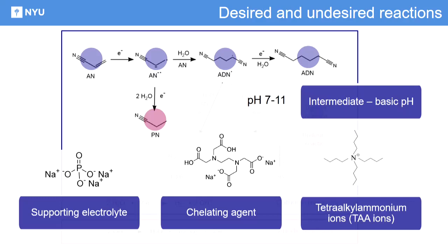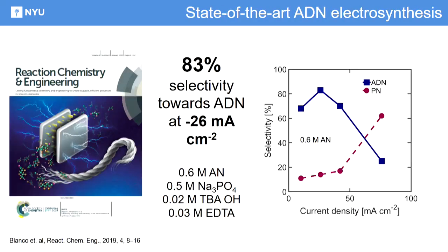So overall, by doing a fairly systematic study on the electrolyte, we were able to find conditions that led to fairly high selectivities, which are starting to approach those reported in this electrochemical process in industry. What we also found is that as you increase current density, of course, the selectivity towards the production of your dimer goes down, and the production of the hydrogenated version of your monomer goes up. So this hints towards mass transport limitations. You're not able to bring enough acrylonitrile to that interface to be able to dimerize it.